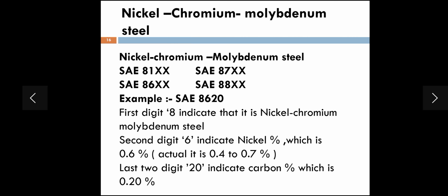Now the next steel grade is nickel chromium molybdenum steel. SAE 81XX, SAE 86XX, SAE 87XX and SAE 88XX, these are the nickel chrome molybdenum steel grades. An example of this steel I have taken is SAE 8620. The first digit 8 means it is a nickel chromium molybdenum steel. The second digit 6 indicates nickel percentage, which is 0.6% nickel in the steel. And the last two digits 20 are the carbon percentage. The 0.2 is the carbon percentage.